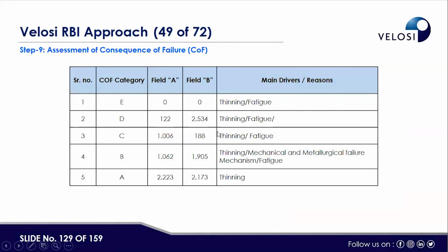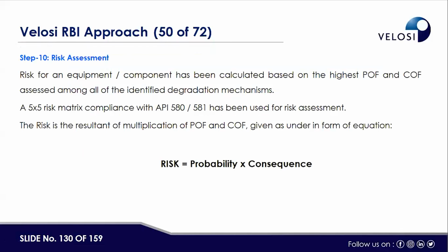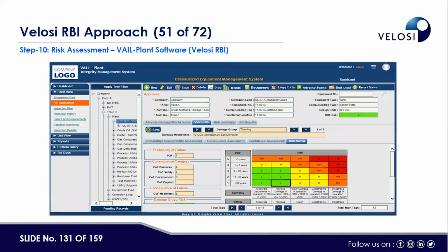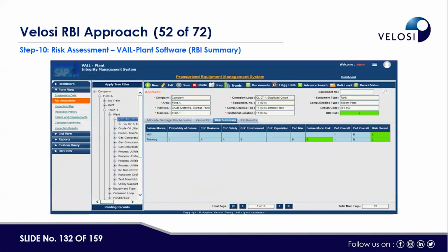So this was the distribution of the equipment in various rankings. From the risk assessment point of view, if any particular equipment is categorized in the highest, there could be various damage mechanisms which may have different POF, but this is the one which is dominant, which is coming as part of the RBI risk. So this could be the assessment of both damage mechanisms, like failure mode B, and then the overall risk is basically low and low. This is the part here. MIC is coming as B.